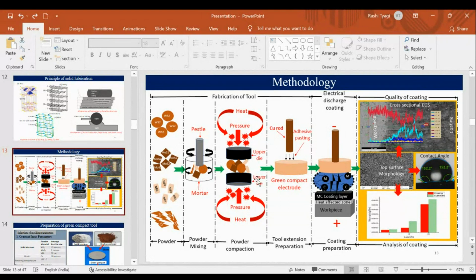So after mixing this powder in the mortar and pestle, we keep it between the dies. Dies means the dies in the hot mounting press. I've told you that we are using the hot mounting press to compact the material and sinter the powders. So when the powder is kept between the dies, we compress it and apply a particular pressure